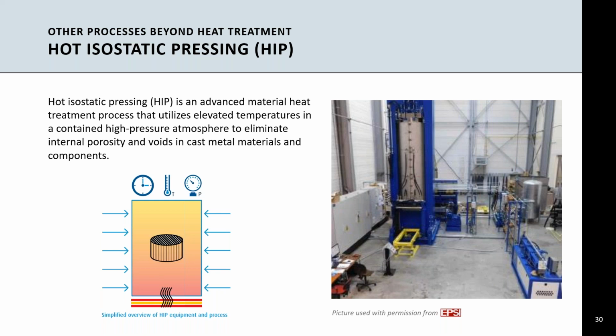Because the metal powder is somewhat porous as it's being laser welded or processed by whatever style of additive manufacturing is taking place, what the HIP process will do is allow the porosity to be reduced. It actually shrinks the material itself and increases wear characteristics, as well as removing any residual stresses that may be in the metal, similar to an annealing process.